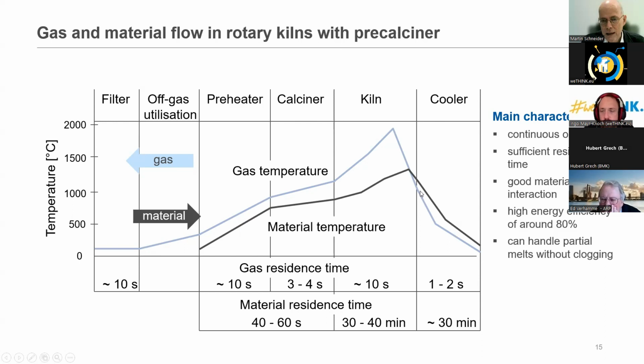And if you go the other way around here, you can see the combustion gases. They start in the kiln here to be ignited. They are preheated, ignited, and you have combustion gases which are almost 1800, 1900 degrees centigrade. The combustion gases are then going this way, and the material is going the other way here. This is the material curve. You have always a strict counterflow, and you may have seen cement plants with so-called cyclone preheaters, in which each stage has an intimate mixture of gas and material. This is the basis for having an extremely high efficiency of clinker production.